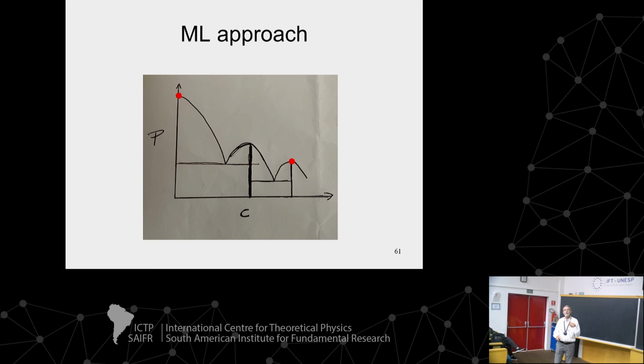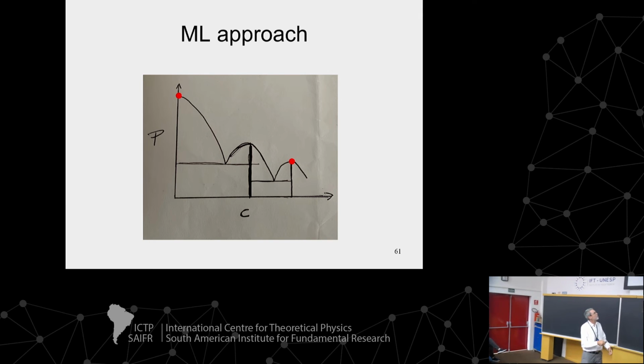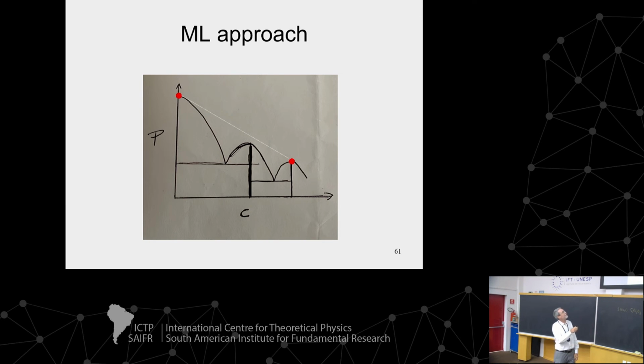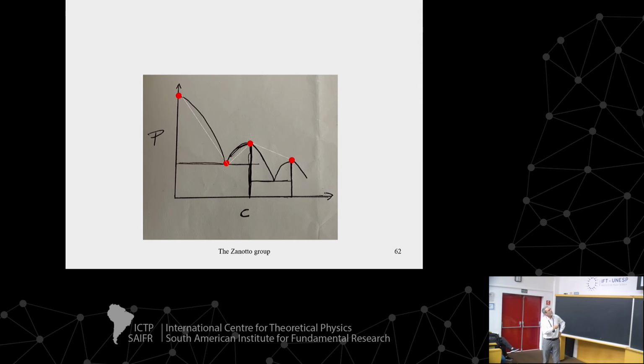So if I only have this data point here and this data point here, no matter which algorithm you use, it will say, well, this is the liquidus. You only have two data points, but this is the best the algorithm can do. Now if I have 1, 2, 3, 4, the best algorithm will say, well, this is the liquidus. Now, if I have more data points, it could say, well, this is the liquidus. And it can even extrapolate here if you come up with a good model. But you can certainly interpolate.